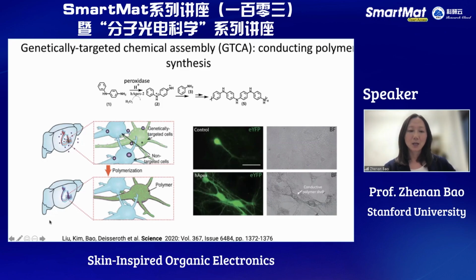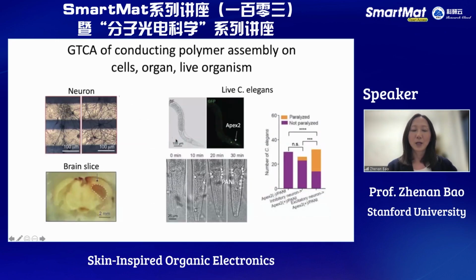That's basically the conducting polymer coating. And we can coat that onto neurons and actually measure a true electrical conductivity. We put electrodes on them and show we can measure conductivity. And this can be done in the brain slice and in a live organism. This is a C. elegans. It's very small, but contains only a few hundred neurons. So very simple, and it's a model system for neuroscience study.